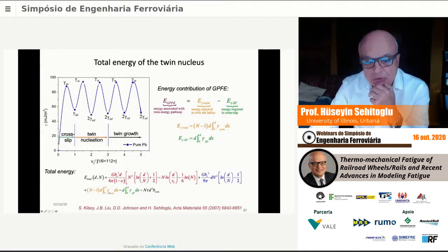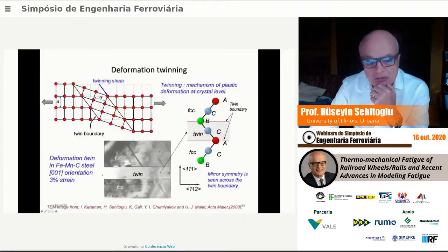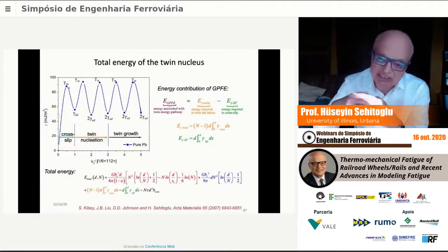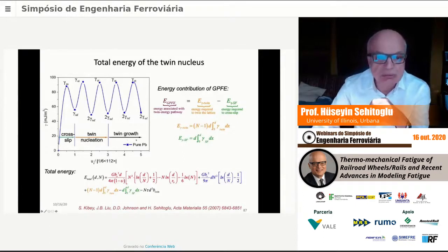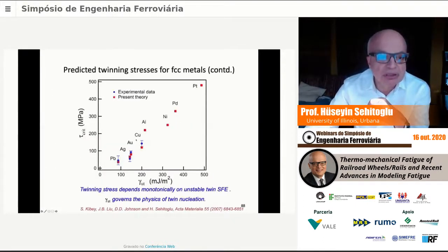We have the terms due to the twinning dislocations, and because we have twin surfaces, there are fault energies associated with that. So we incorporate that in a model. This is shown here. These are the energy barriers that we have to overcome as the twin grows at the lattice level, and we're able to predict the twinning stress. We did calculations for lead, silver, gold, copper, aluminum, nickel, palladium, etc., and also the iron manganese steels.